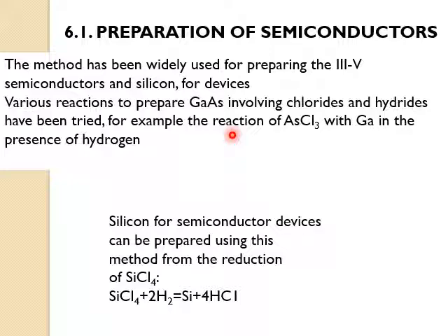For example, one of the reactions is where arsenic chloride is reacted with gallium to form gallium arsenide in the CVD method, in the presence of hydrogen gas; the carrier gas will be hydrogen. And here is another synthesis, that is the synthesis of silicon. Silicon is a semiconductor material and it is used in many electrical devices. It can be prepared by the CVD method, the chemical vapor deposition technique, from the reduction of silicon chloride. Silicon tetrachloride reacts with hydrogen. It is reduced by hydrogen. It is converted to silicon and hydrogen chloride, and this silicon is deposited on the substrate. Silicon chloride is converted into vapors with hydrogen carrier gas, and when it deposits on the substrate, it will form very thin silicon layers.